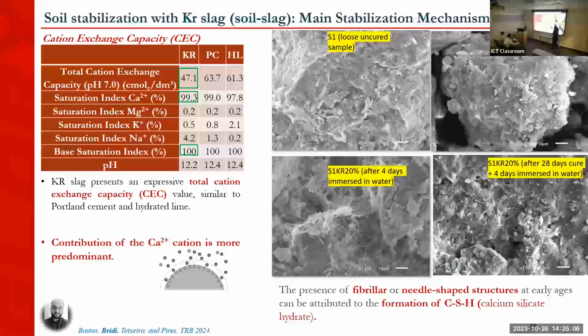Also, we took this soil sample and we evaluated it in the microscope after 4 days and after 28 days. What we observed when we mixed it with KR was the appearance of those fibrillar, needle-shaped structures. And this is also observed when Portland cement has its hydration reaction occurring. It can give extra strength to the material, makes the microstructure more dense and increases the strength.